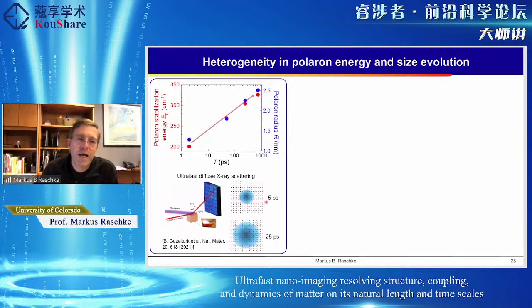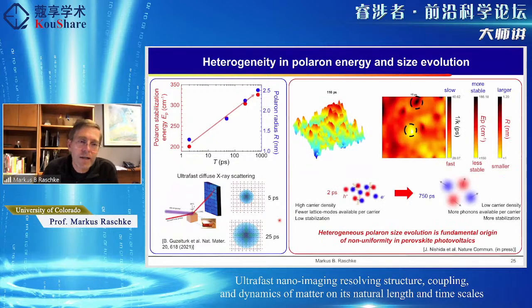This is something which has been hypothesized previously, actually, from ultrafast diffuse X-ray scattering, where people have observed signatures which suggest that more and more neighboring lattice sites get locally distorted as a result of this electronic excitation. And so with this model now, we can turn our full spatio-temporal data set into a real movie, which we then fit, and we can extract time slices of polaron stabilization energy and radius.